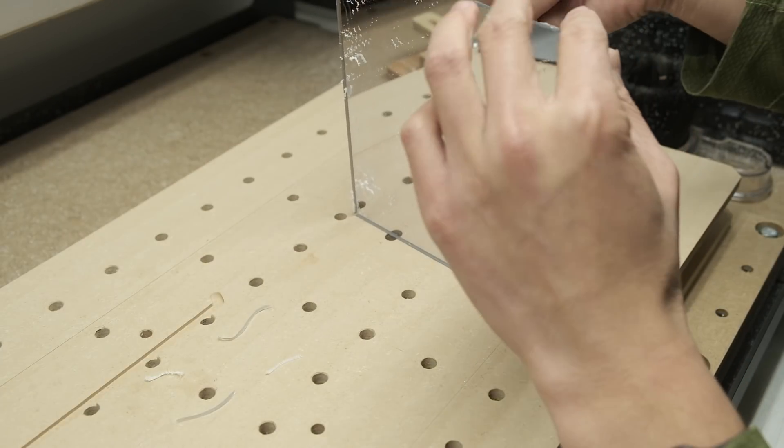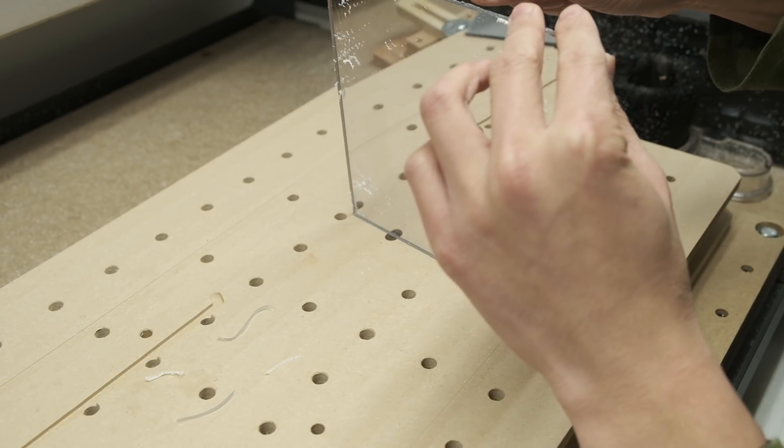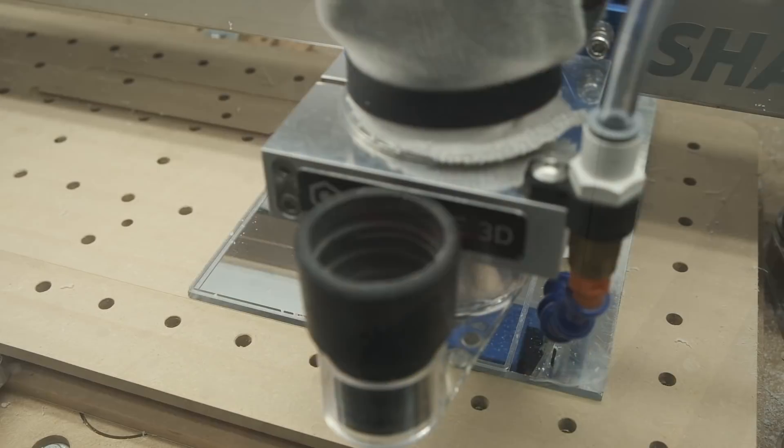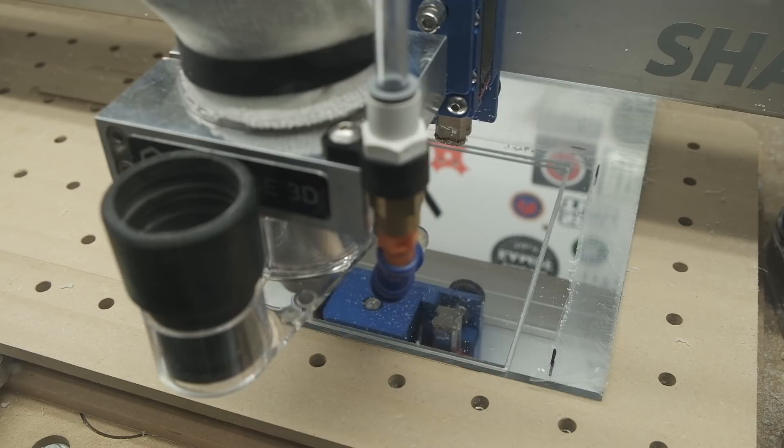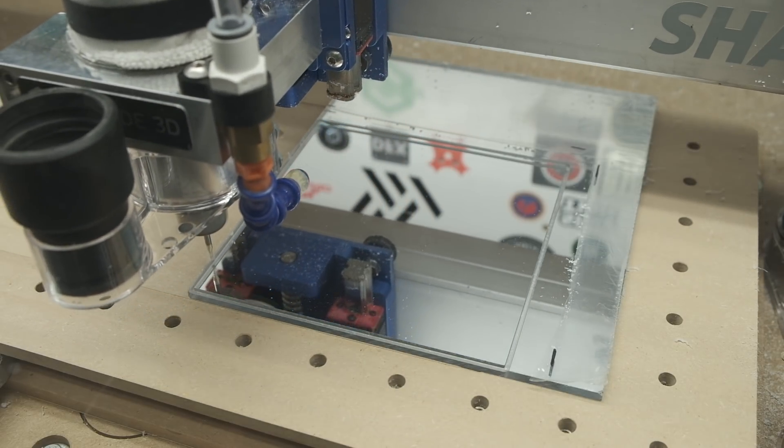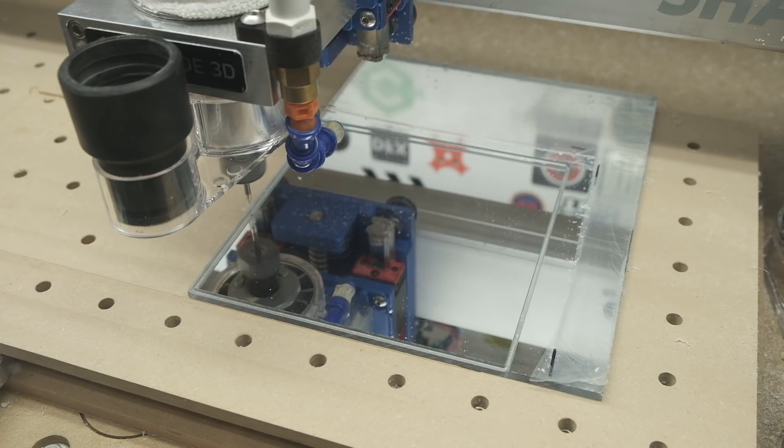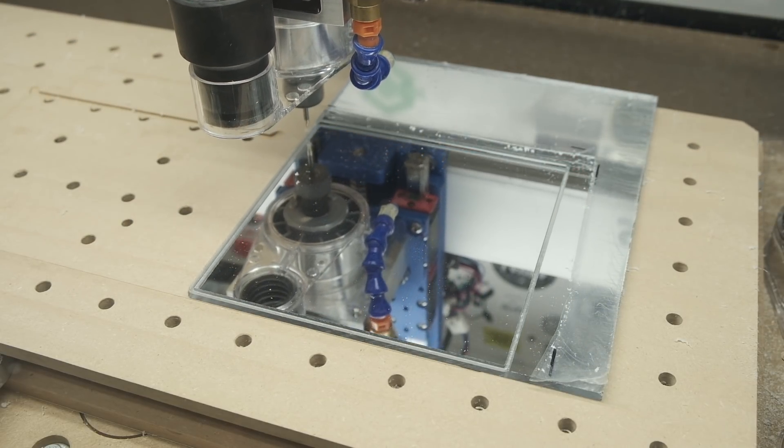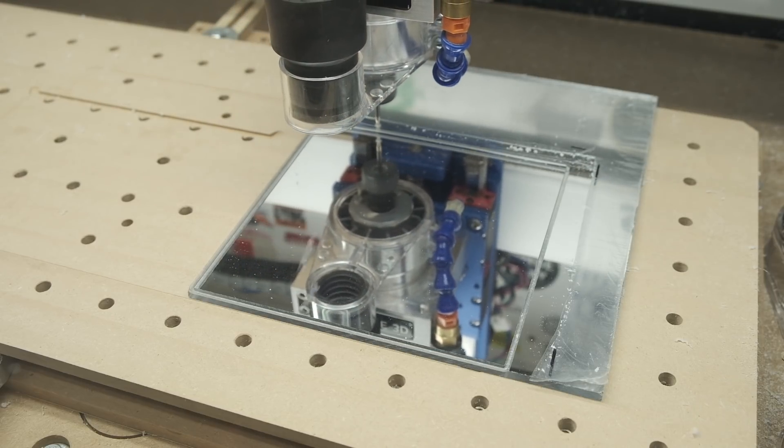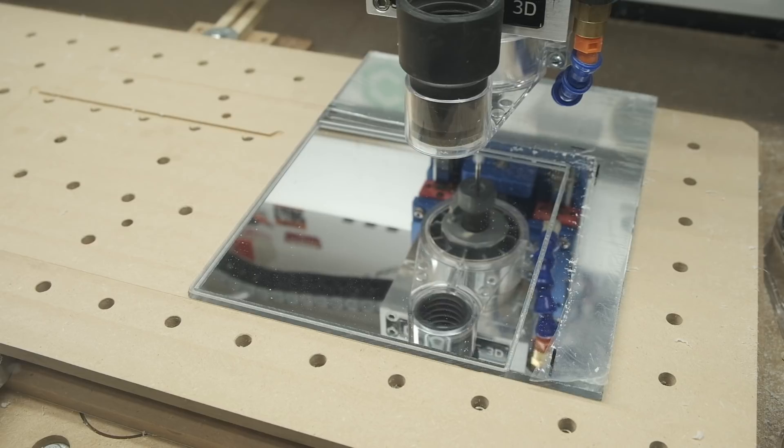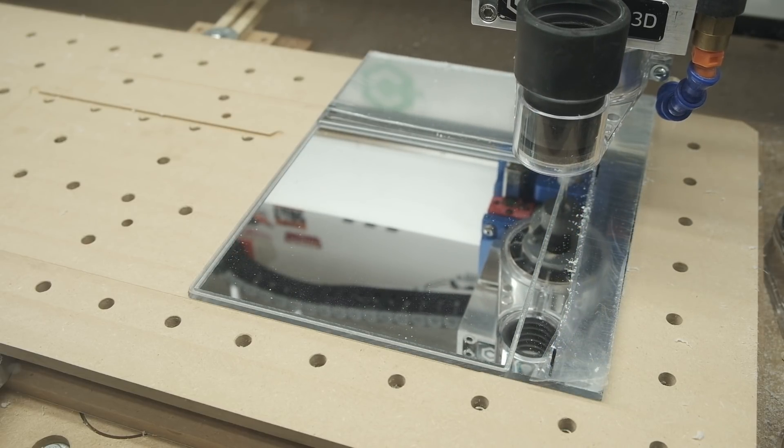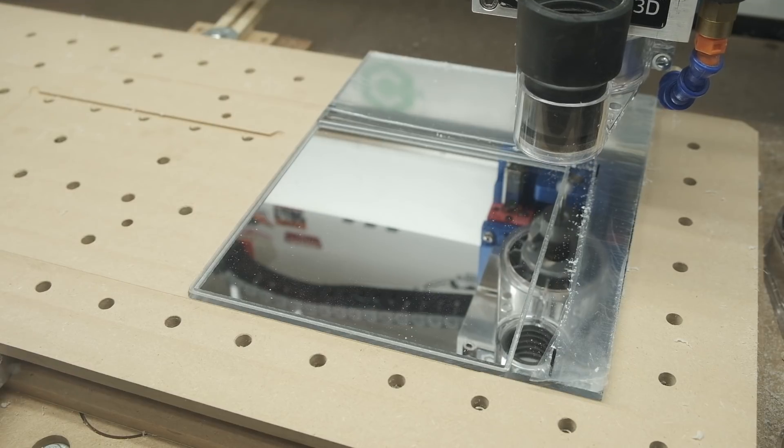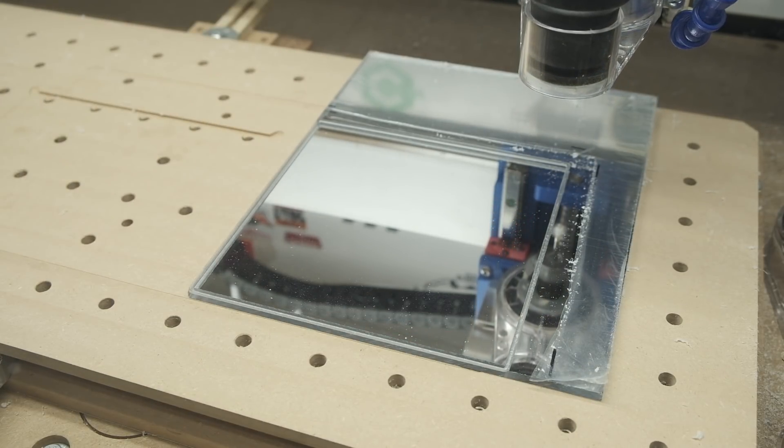It wasn't until much later that night, right before bed for me, that I realized the likely cause of my poor experience cutting acrylic. Most commercially available acrylic comes in two varieties, cast and extruded. Extruded acrylic is generally cheaper and it cuts easier with a laser. It's also a little softer and has a lower melting point than cast acrylic. Of the dozen or so mirrored acrylic vendors I could find with a quick google search, about half of them said they were made from extruded acrylic. The other half just said acrylic. None of them ever explicitly said they were made from cast acrylic.